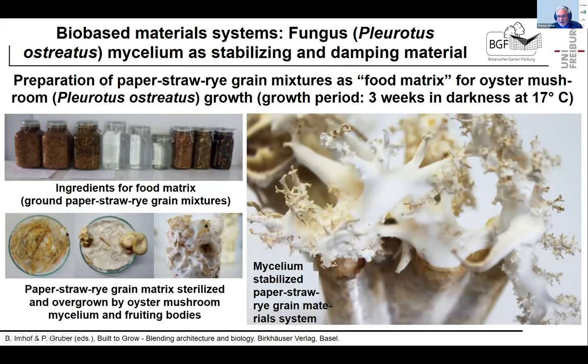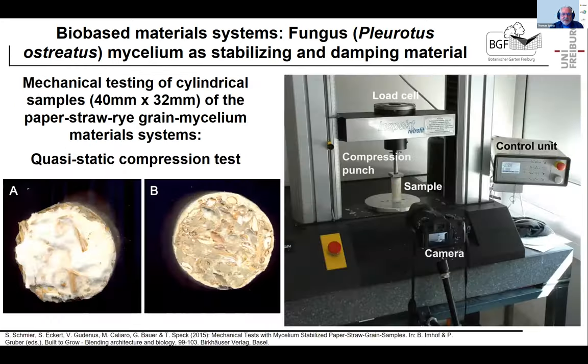Here you have the food matrix, and here you have the fungi mycelium growing, and it's really a full intergrowth, a three-dimensional connection in this kind of matrix. What we did then, we let these things grow into samples without compression, cylindrical samples which were originally 80 millimeters long and 32 millimeters wide. We cut them into halves, and then we tested them mechanically.